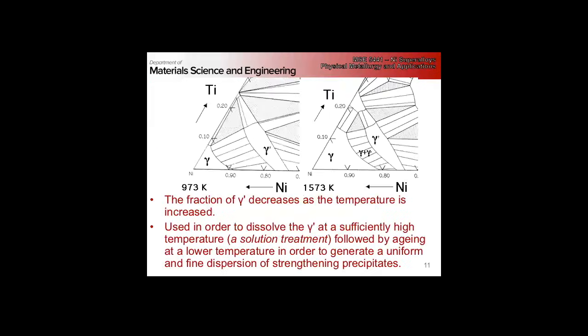Okay, so looking at the phase stability with temperature. Personally, I hate ternary phase diagrams, they always confuse me. But we can see here, basically, if we look as we go up in temperature, the gamma phase field expands. And if you do your lever rule calculation, that means at the same concentration of alloying, as we go up in temperature, the fraction of gamma prime is going to decrease. That makes sense with what we said before, right?